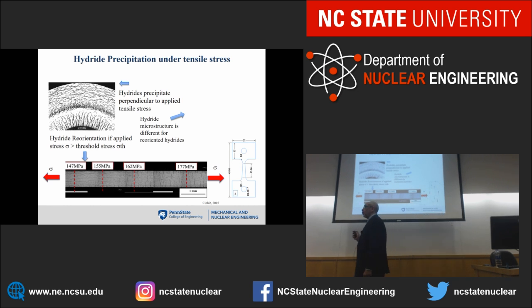So the way to check that, we took a tapered sample like this, right? A dog bone sample. I pull here, but then the cross section varies here, right? So for the single load, the stress is much higher here than here. And I have a gradient of stress. I can then do the experiment, and then I etch. I cut it across this way, right? And then I check where I see reoriented hydrides, and I can calculate the stress at each place.